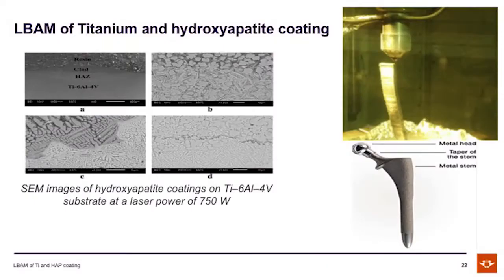There was then a need to coat implants that are made from the titanium alloy grade 5. We then used the hydroxyapatite coating. This is our own photo taken at the National Laser Center of an actual hip implant that was being built under the laser system. And these are some of the results showing good bonding and good results from that study.